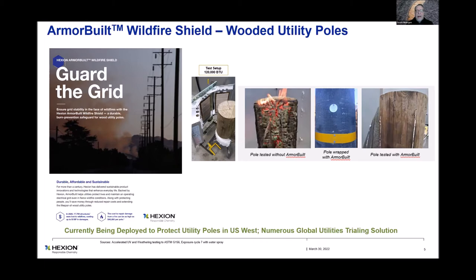On the testing and diligence side, look at the picture just to the right of Guard the Grid. That is a correlative test apparatus, three burners, just 9 inches from the face of the target material. It puts out 2,100 degrees at 120,000 BTUs, and wrapped with ArmorBuilt, you can see on the far right, that is the result of the protected pole after a 10-minute burn at 2,100 degrees Fahrenheit at 9 inches.